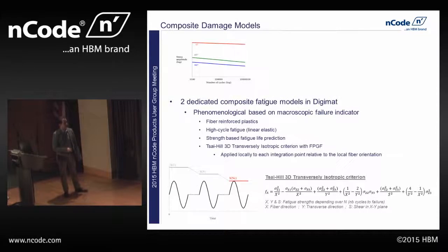So this is the damage model that we're going to be using then. So then how do we go about generating this damage model? Because as you can see, we've got 3 different parameters in here that we need to fill in. And obviously this is a relatively complex situation. I guess one thing I missed here that I want to come back and touch on is that when we run this type of model, we're going to end up with something like this, where basically we can vary that individual orientation and see a different SN curve for each individual orientation. So, this is a representation of that fact that the SN curve changes as a function of the loading and the fiber orientation.